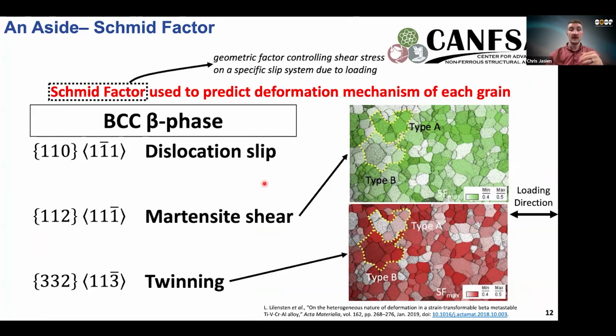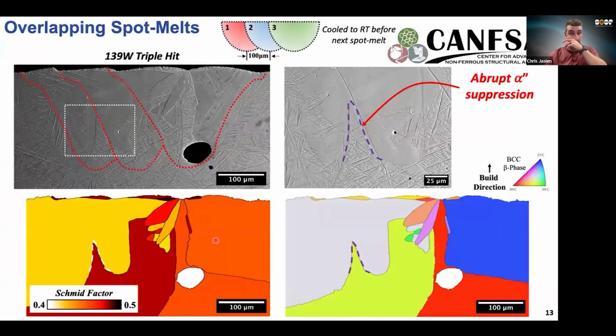when stress is applied. So for instance, what we did with this material is we looked at the martensite shear system, which is what is dominating this material. And so we went and back calculated from our grain orientations what the Schmid factor may be, where a higher Schmid factor shows a greater propensity to transform, and conversely lower would mean you wouldn't expect much transformation at all.